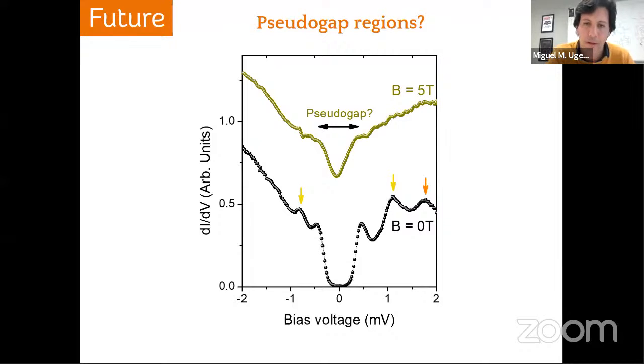I have this slide to show that. This is the same region at 0 Tesla and 5 Tesla, well above the critical field, and we still see something. And that's what you saw in the upper curve in the set with evolution. This is clearly evidence to me that disorder, not crystalline disorder but electronic disorder, which is extremely interesting, is playing a significant role in your data. Yes, but perhaps we can talk later, because we are puzzled about this. We have also measured tantalum diselenide, and we clearly see this feature as well. And it's not clear at all that it's superconducting anymore.